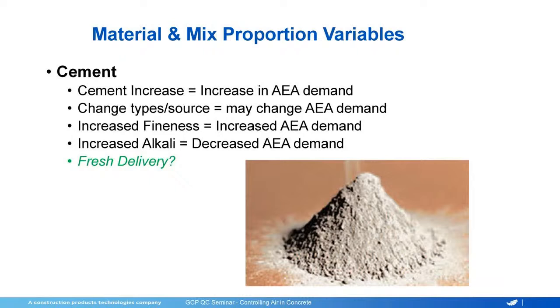The higher the alkali of a given source of cement, the easier it is to entrain air. So if I have a source of cement and my alkali is at 0.4, a month later it's up to 0.6 or 0.7, it's going to be a lot easier to get air into that concrete. So that's one of the things to look out for. And then I get asked this question often: what if I just get in a delivery of cement? Sometimes it seems like that causes my air to go haywire. It can happen. Any of those things that I just mentioned can be changing with a new load of cement.